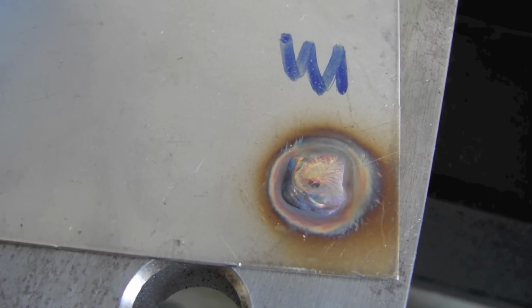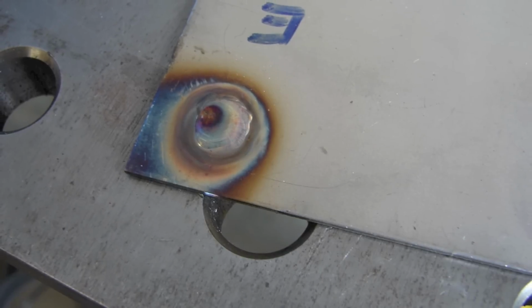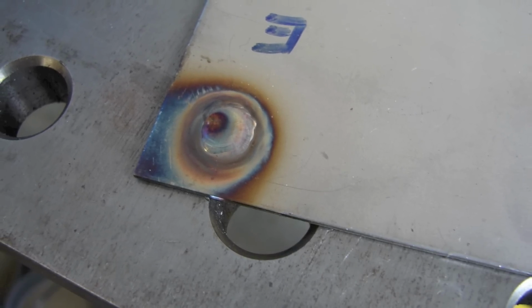And what it does is it takes a lot of heat away. It traps a little argon on the backside, and I'll show you the backside in just a minute. This is the Everlast. The first one was the Miller, the hole fill. Both of them are very similar in how they did there. Plenty good low-end characteristics to do .050 stainless. There's the front side. There's the back side where it was against the copper. Front side again. Back side. You can see it's pretty shiny, not quite as white as it would be if it was good argon shielding, but you don't always need perfect. Sometimes that would be a heck of a time saver rather than having to purge the back side with argon.